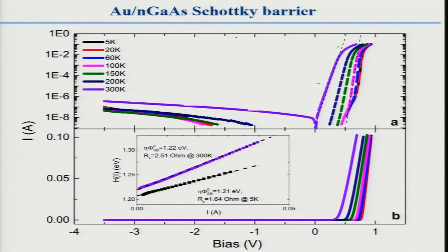Here are the Cheung plots for the same junction. You can see it's very linear. This is very well behaved. We can extract from here a series resistance for our gallium arsenide at 300 Kelvin of 2.51 ohms. At 5 Kelvin, it's 1.64 ohms. Those are low resistances. And so that's why we get these nice logarithmic regions here. And you also get the product of the ideality and the 0 voltage Schottky height as 1.2 volts here and 1.22. Notice that this is not changing, and I'll give you a reason for that. So those are numbers which are sort of interesting.